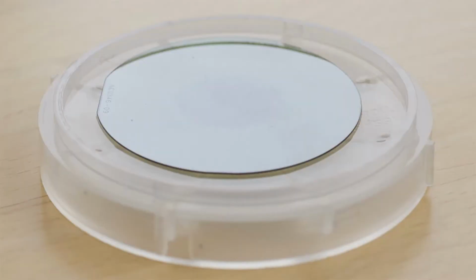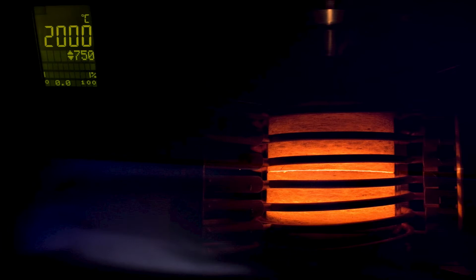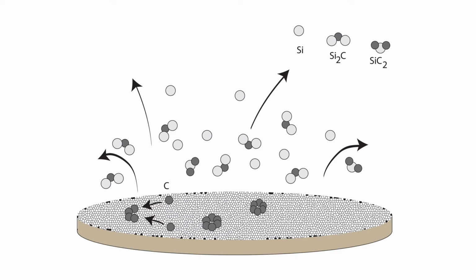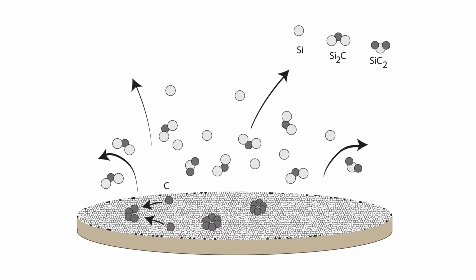And in that one, we go back to the wafer, which is grown by the PVT method. Then you grow boules, cut wafers and polish them, and then you have a substrate for further processing. And in our growth, we have been using high temperature implementation. So for the PVT growth, we do the growth. But for other purposes, we can also heat up the silicon carbide. When you heat up silicon carbide, you have the silicon and carbon bearing species, and they create vapor species. Then you have silicon, Si2C, SiC2, and so on. When you heat this up, more silicon leaves the surface than carbon. So then you have one layer of carbon on the surface of the silicon carbide.